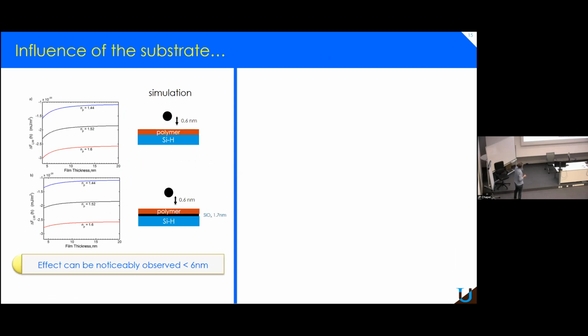So here is just some question that some of the reviewers asked us. So what is the influence of the substrate? Obviously, because this is the main concern. And we can see, for example, here you have a system with an HF-treated silicon wafer without the oxide layer, that people are using all the time. And so here by simulation, you can see that we don't see any effect up to, let's say, 6 nanometers. Below, it could be complicated to make a difference between the effect of the substrate or the effect of the film.